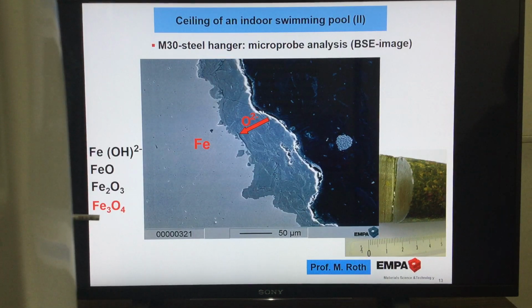What do we know about Fe3O4? Fe3O4 is very stable and very dense, and if this were here, Fe3O4, then the diffusion rate of oxygen is extremely low. So it would take a long time, or even no oxygen diffusion is possible, so that this layer would go more and more inside. That means if we find this stable oxide with high density and low diffusion rate for oxygen, then it would be fine.